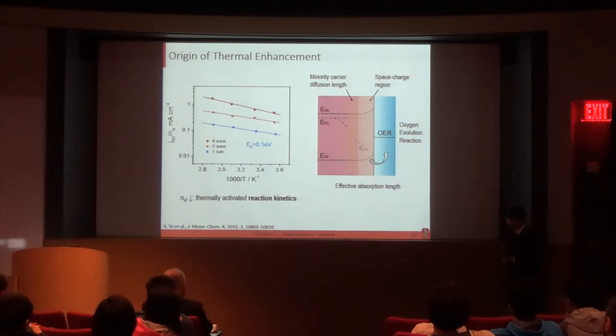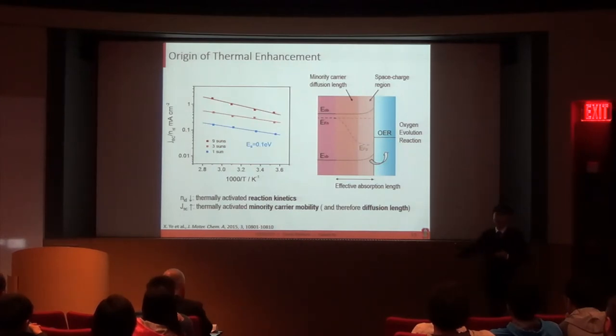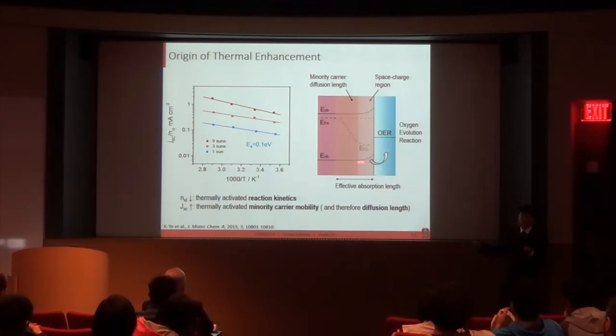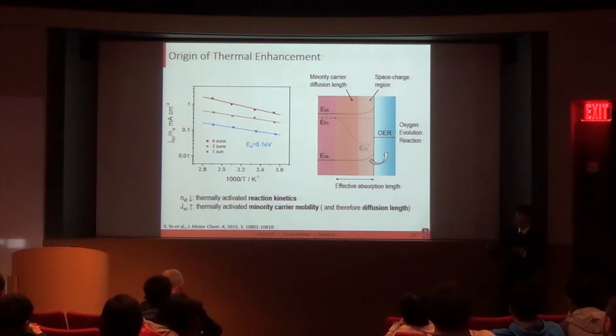to 1. And for short circuit current, we know that the mobility in hematite increases exponentially with temperature. So that could possibly cause a longer minority carrier diffusion length if the carrier lifetime doesn't strongly depend on temperature. A longer minority carrier diffusion length gives you a longer effective absorption length and therefore a larger short circuit current. So a combined effect of these two gives rise to a thermal enhancement that we see in